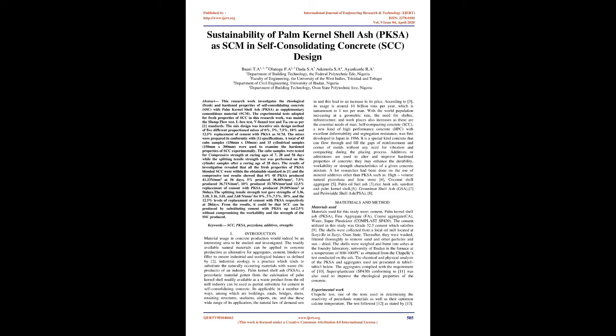The results of the investigation revealed that all the fresh properties of PKSA blended SCC were within the obtainable standard, and the compressive test results showed that 0% of PKSA produced 41.33 N/mm2 at 56 days, 5% produced 38.40 N/mm2, 7.5% produced 36.71 N/mm2, 10% produced 33.78 N/mm2, and 12.5% replacement of cement with PKSA produced 29.50 N/mm2 at